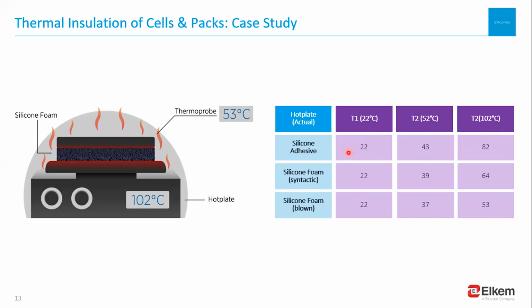For a temperature of 52 degrees C on one side of the silicone, the opposite side of the silicone was kept at a temperature below 40 degrees C in the case of the foams. And at 102 degrees C, the opposite side of one of the foams, the blown foam in particular, saw a temperature of only 53 degrees C. That's approximately a 50% reduction in temperature.